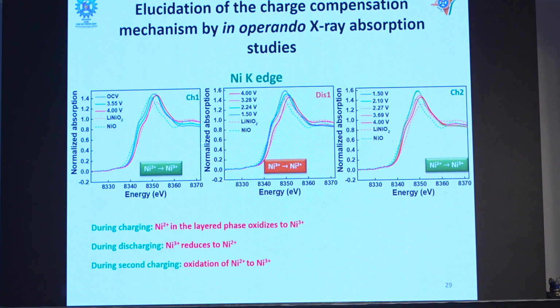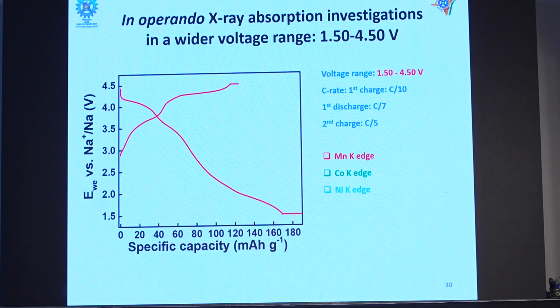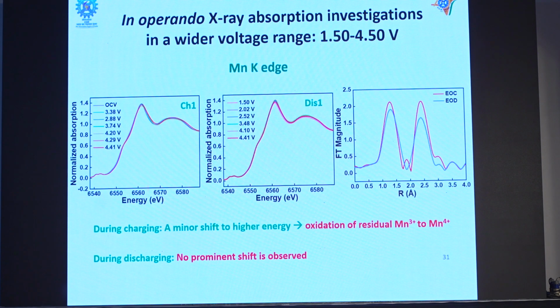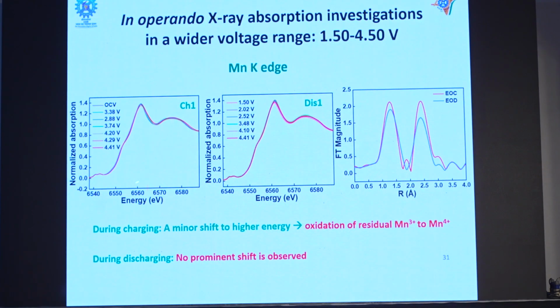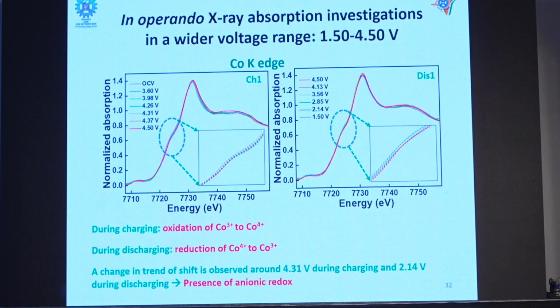For the nickel K edge, we are also seeing nickel 2 plus, nickel 3 plus oxidation reduction reactions. It's again what we have expected. And when we increase the voltage range to 4.5 volt, the manganese, interestingly, is not very active. So during charging, we are seeing a minor shift rather than the increased shift we have seen during the operation voltage of 4 volt.